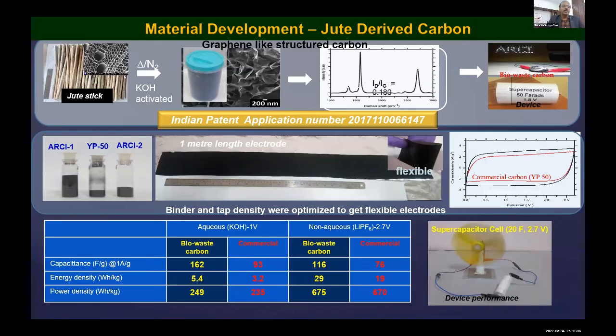And what we did is, can we do this within the country? Initially we started with jute sticks. Jute sticks are useless material because once you take the jute skin for the jute bags, the sticks are only firewood, but they're very lightweight with a cellular structure. We converted them under nitrogen atmosphere to carbon with a proper KOH activation process. We get graphene-like carbon with a very high surface area, above 1500 meters square per gram. We demonstrated that its performance, as you can see here in the cyclic voltammetry, is on par with YP50. And the cost is pretty low. So we demonstrated a supercap of 20 farad.